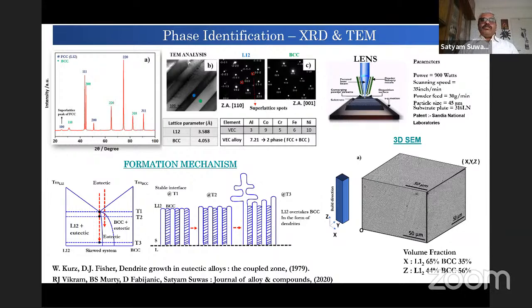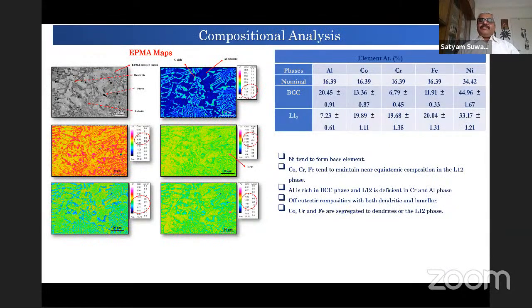We carried out thorough characterization of this, and we could stabilize the BCC phase and L12 ordered phase and BCC disordered phase as a result of additive manufacturing, which was slightly different from what is generally made by the casting route. In that case, the FCC phase is disordered and the BCC phase is B2, but the additively manufactured material has ordered FCC and disordered BCC phase.